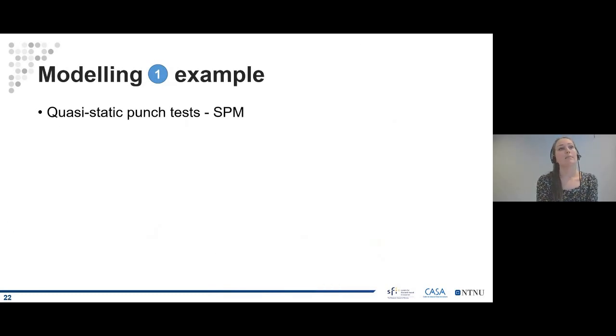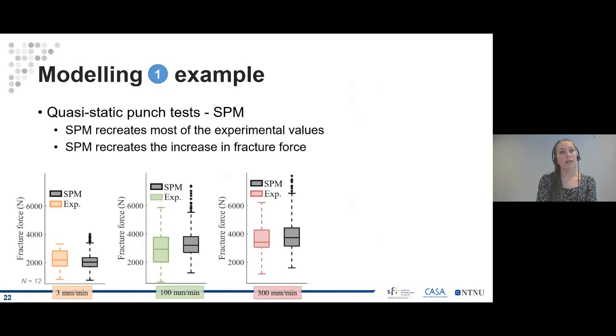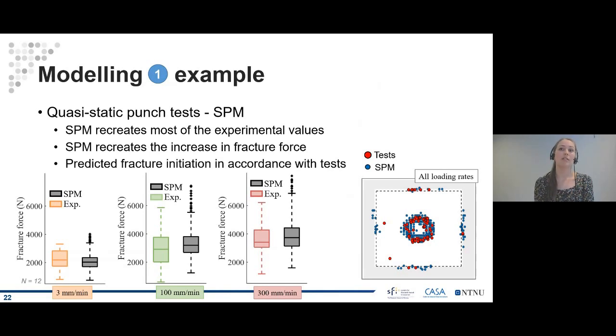Right, then over to the SPM results. These box plots compare the fracture force from the experiments and the predictions from the strength prediction model. The SPM results are shown in gray. We see here that the model is able to recreate most of the experimental values. We also see that it can predict an increase in the fracture force with the loading rate. Also, the predicted positions of fracture initiation correspond well with the tests. The test results are here shown in red and the model results in blue.